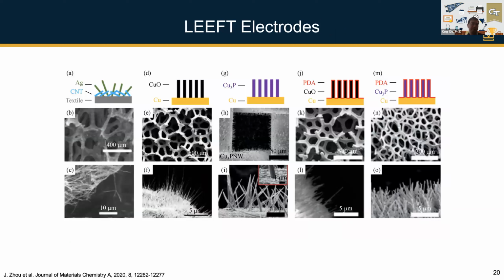Okay, now I just want to talk about the challenges we are still facing. As we demonstrated, it's a small scale, right? For this kind of point of use, that's no problem. We want to push the technology forward for larger scale and longer uses. One of the biggest challenges is really the electrodes, especially those with the nanowires. If there's no nanowire modification, it's already commercially available, just using the copper wire. That's fine, but we're still studying how to make sure the copper release is more uniform, so it can last longer.